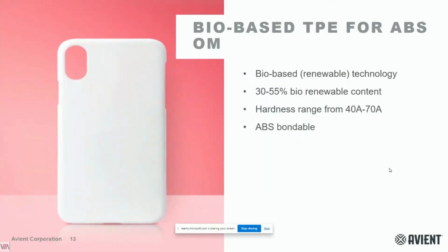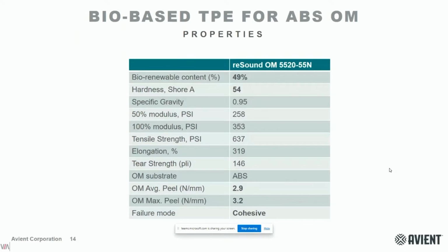We also have bio-based TPEs that are suitable for molding with ABS and styrenic substrates. Also with a wide range of Shore A from 40 to 70. Here again you see an example of one of our available grades in Europe, a 55 Shore A solution in natural.